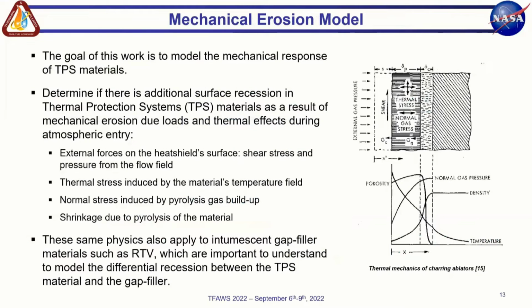The goal of the full-scale modeling with PATO is to predict the mechanical response of TPS materials, and specifically to determine if there is additional surface recession in the TPS surface as a result of mechanical erosion due to different loads experienced during atmospheric entry. And these loads might be, for example, the external forces on the heat shield surface, like the shear stress and the pressure from the flow field, thermal stresses induced by the material's temperature field, normal stress induced by the pyrolysis gas buildup, and also shrinkage due to pyrolysis of the material itself.